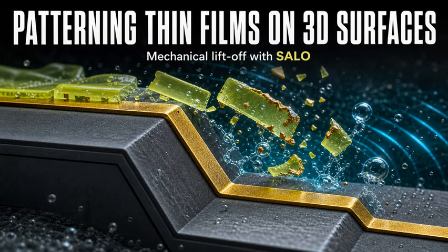Yeah. But SALO gets around this by completely ditching the solvent approach. Okay, so how does that work? You drop cast your standard IP-Dip photoresist onto your 3D target, print your scaffold via 2PP, and coat the entire thing with your thin film. Yeah, and then instead of harsh solvents, you drop the sample into an ultrasonic bath filled with isopropanol. Just standard IPA? Just IPA. Yeah. It has low surface tension and low vapor pressure, and that creates stable cavitation during sonication. So you get these microscopic bubbles that collapse and generate highly localized microjets and shockwaves. Yeah, and this mechanical shear force is what physically snaps the scaffold off, bringing the unwanted thin film with it. Because it relies on mechanical shear rather than chemical solvent access, SALO successfully lifts off highly conformal ALD coatings.